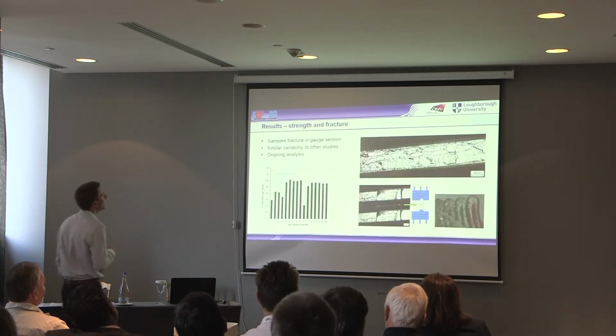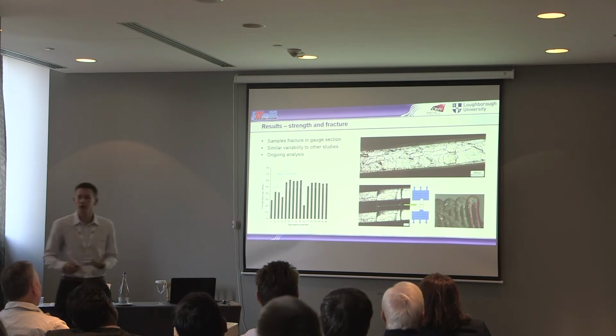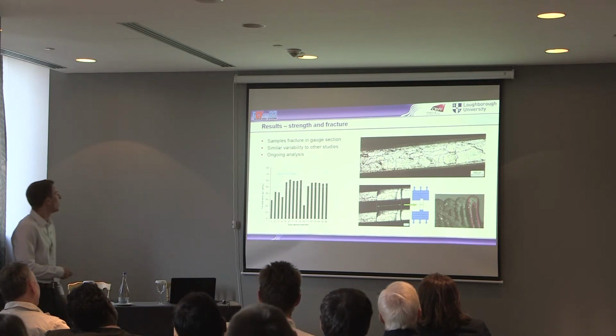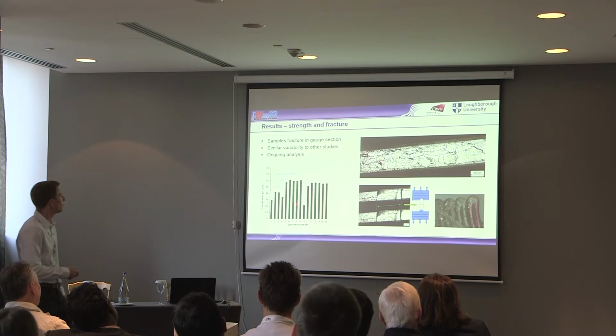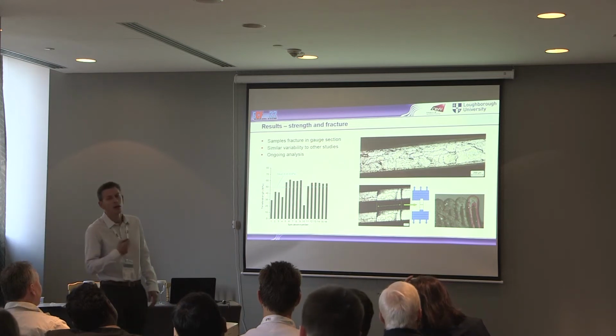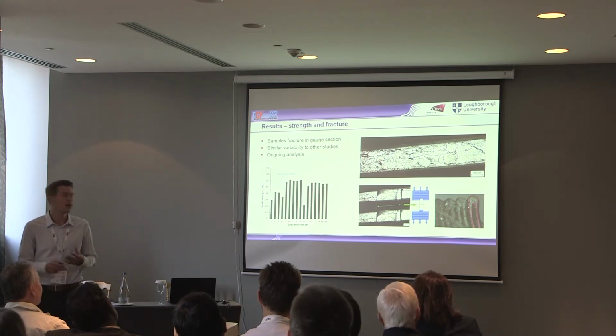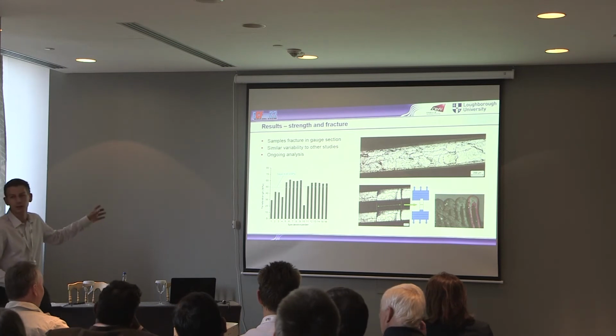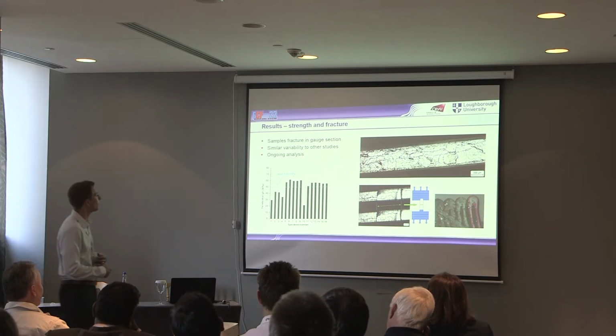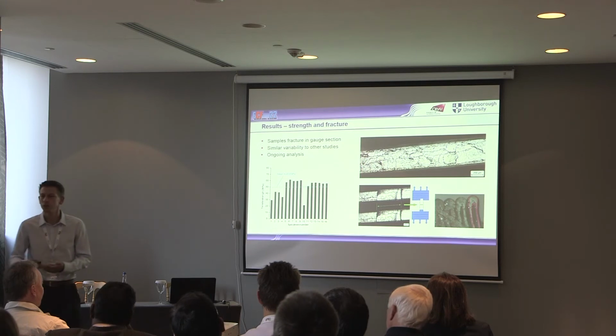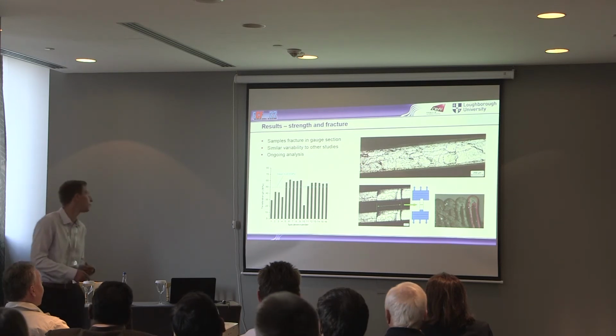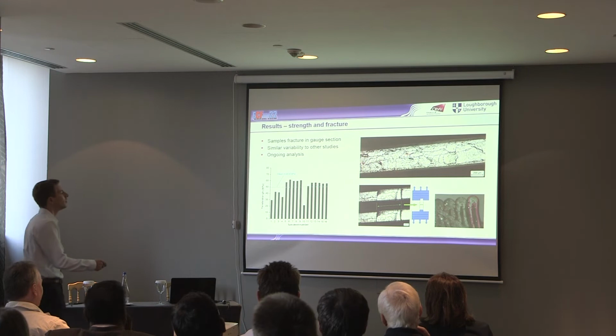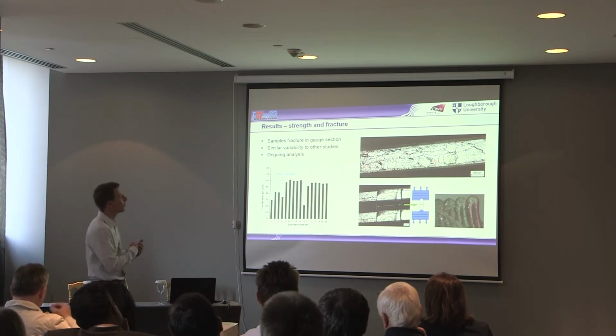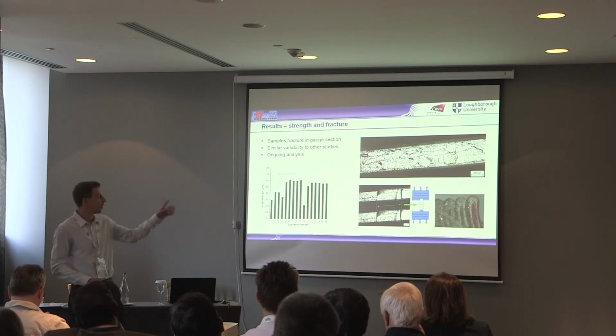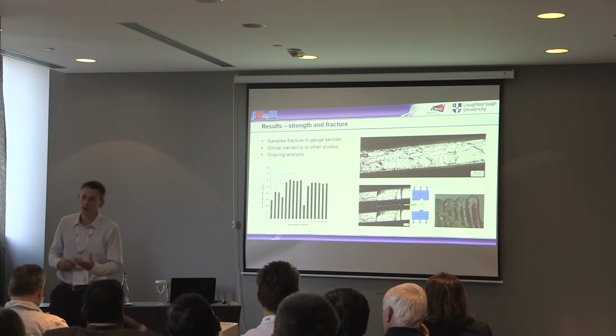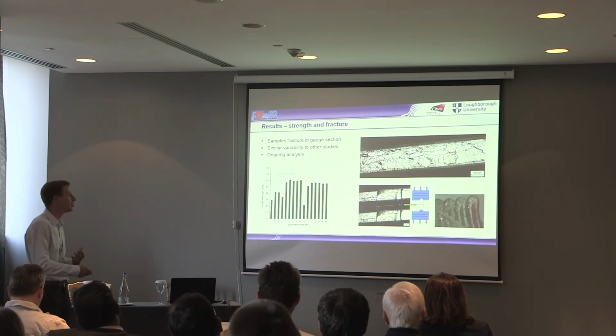And then in terms of the mechanics, the fracture and the strength of these parts, we're getting pretty consistent results. There are a few wildcards here, but according to other studies in the literature, they have as much variability or more than this in mechanical properties and repeatability. This is just the first set of tests we've done for this. And you can see immediately, this is the fracture surface. We've got a full clean fracture. It's very easy to analyze what type of fracture, and to identify the direction where the crack was initiated.